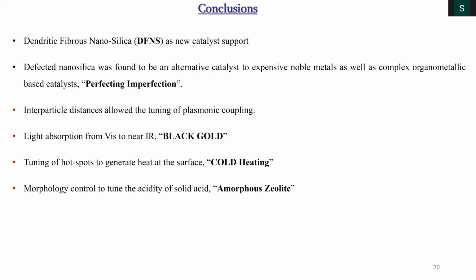We also showed that one can tune the interparticle distances between the gold particles to give you the black gold, which absorbs visible to near IR light. And then that black gold can be used to harvest the photons from sunlight and produce heat only at a specific point of the surface, keeping the entire thing cold. And then I also showed you in the last few minutes that one can tune the morphology and the interfaces between the silica and aluminum to give you a very strong solid acid, which is this fancy name of amorphous zeolite, which has acidity like zeolites and porosity like amorphous aluminosilicate. So ideally, these are amorphous aluminosilicates and not zeolites because they are amorphous.